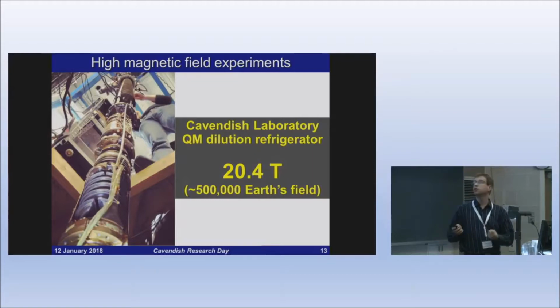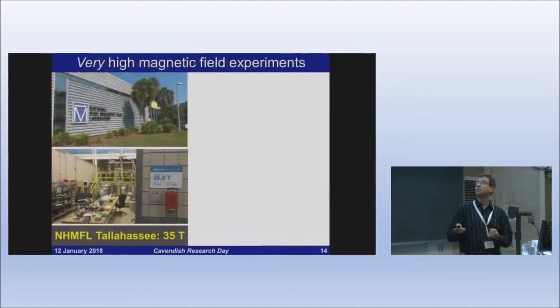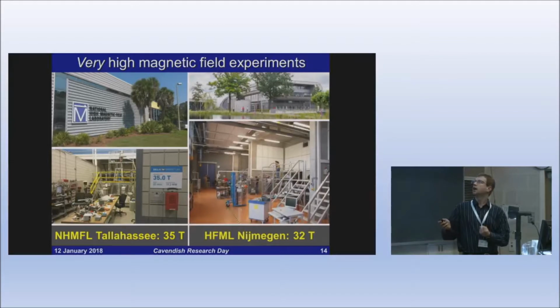and yet sometimes, because these can be very small signals, this is still not large enough for us, for which we need to go to national lab facilities in Tallahassee, Florida, where they get up to 35 Tesla, or at Nijmegen in the Netherlands, up to 32 Tesla. We've worked in both facilities. Now, we would think that this isn't a large increase from the 20 Tesla that we get here at the Cavendish, but in the regime where our signal is suppressed, the signal grows exponentially with magnetic field. So this can provide a huge boost, the difference between seeing nothing at all and a very good signal.